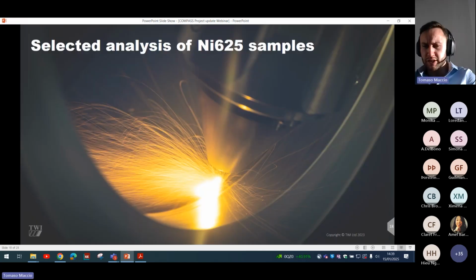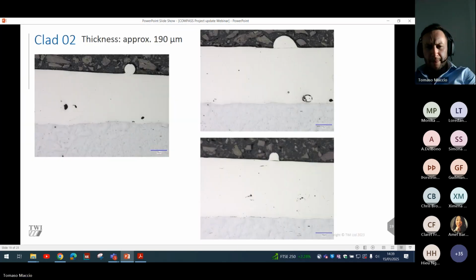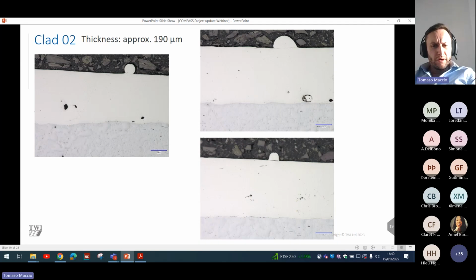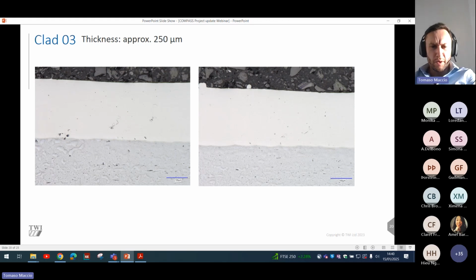This is just a small selection to look at some of the results that we got from this test series. So we did a full analysis of all of the samples and SEM analysis for a selected few samples. Again, some small defects on these, and the thickness is not as expected on these, but this is more where we were looking at.